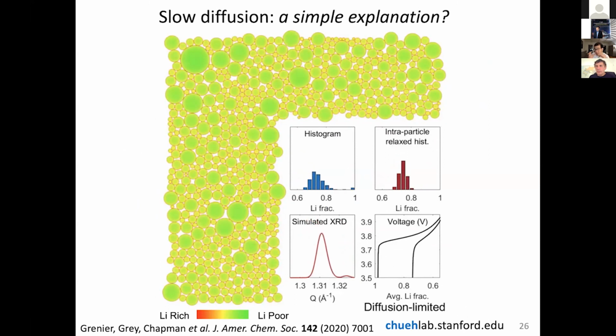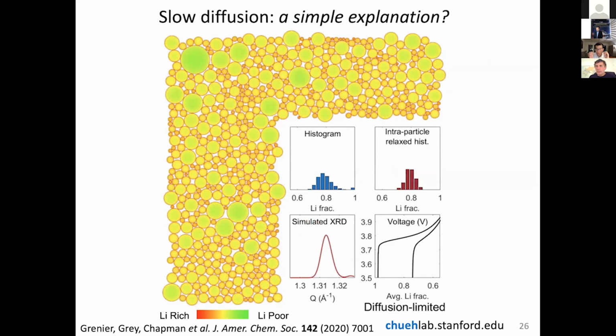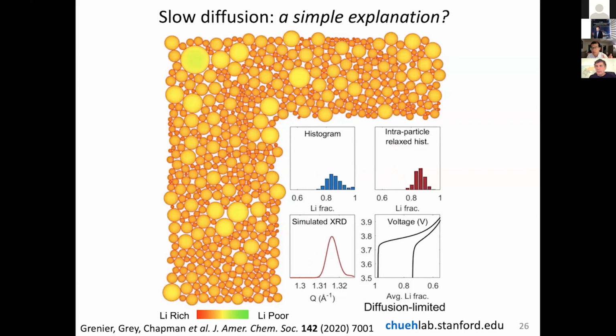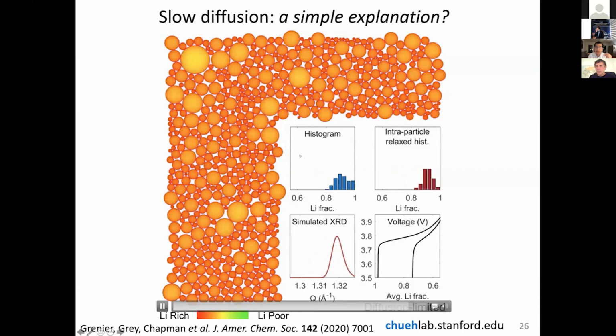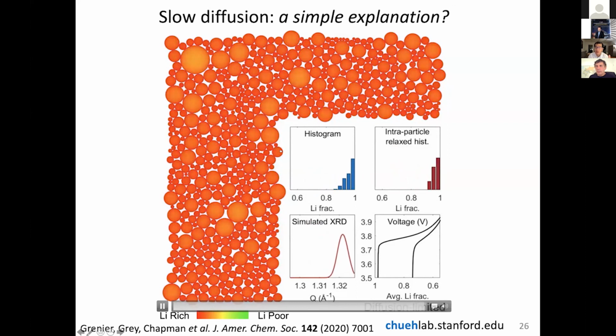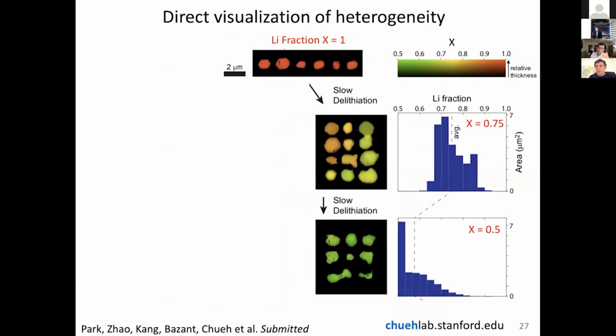However, if we took this picture, and we took images of all these particles, we would expect a very standard behavior of a single peak histogram. So now, let me show you the picture. We took these particles, we allowed the lithium to move freely within the particles, but not between the particles. And then let me show you what happens. When you remove lithium very slowly, you see this standard single peak distribution. There is heterogeneity between the particles due to size effects, for example, and other variations, but it's a single peak.